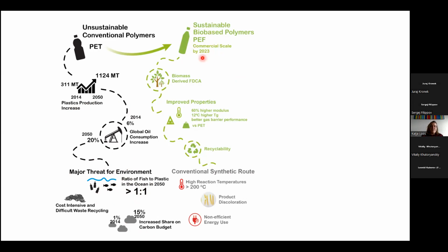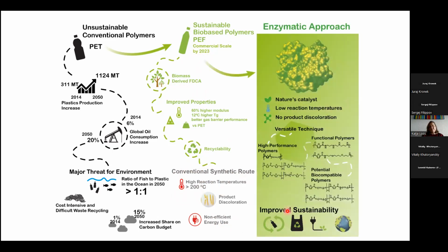And one that's commercialized, that's polyethylene furanoate, PEF. It's a biomass-derived FDCA. I come back to that later, but this polymerization has a problem. If you do a melt polycondensation, it forms furfural because it's a furan-based monomer, and it leads to discoloration. So this is something that in the whole furan-based monomers, if you have the temperature too high, it gets darkish brown.